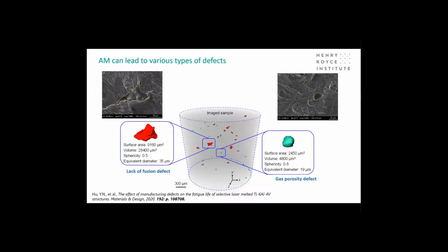As we'll see, I'm sure, in later talks, there are various types of defects that can be introduced. Here I just show two types of defects: a lack of fusion defect on the left, and gas pores or keyhole pores that are formed during the additive manufacturing process on the right. On the whole, the gas pores and keyhole defects tend to be circular or spherical in nature, whereas lack of fusion defects tend to be more angular, and often, if the conditions are not appropriate, you can end up with large lack of fusion defects, which can be very important in terms of compromising the fatigue life. So it's possible using CT to understand the relationship between the additive manufacturing conditions and the types, locations and sizes of the defects that you're introducing.